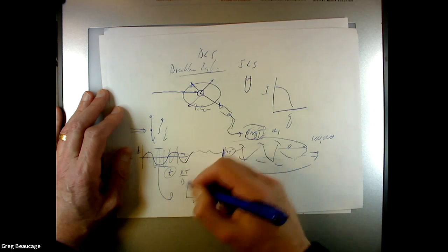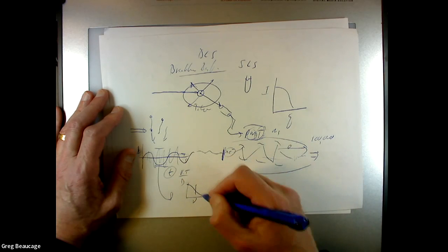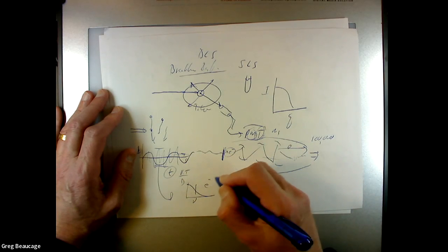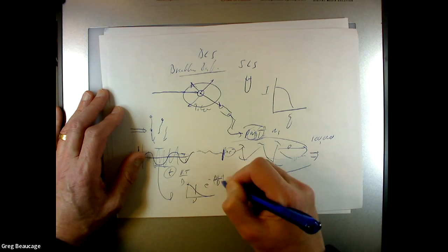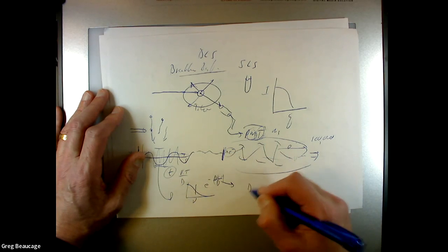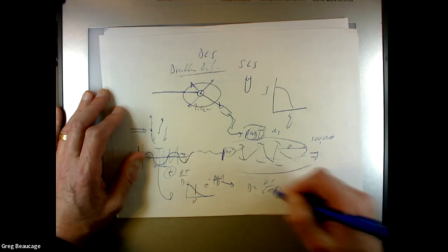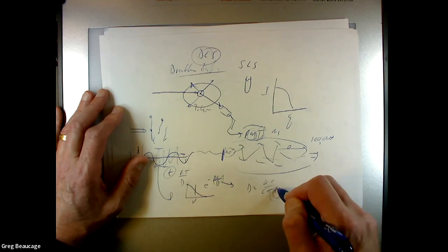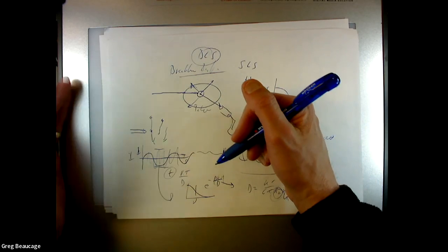But because it's like a noise pattern, it's going to be a decay. So the Fourier transform of that is going to be this decay pattern. The decay of that thing is going to follow an exponential related to the diffusion coefficient, kT. And the diffusion coefficient you get from that is going to be Stokes' law, giving you the hydrodynamic radius, given some viscosity. So this DLS machine will give you the hydrodynamic radius, and the flow thing will give you the hydrodynamic radius too. So there's two ways to get it.